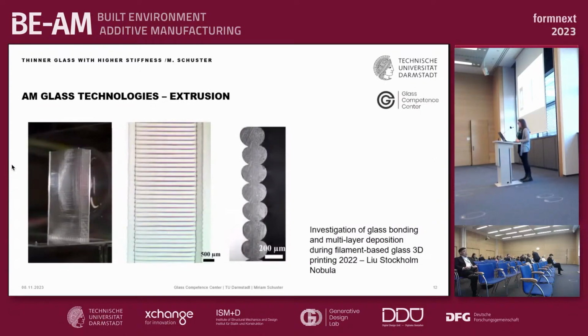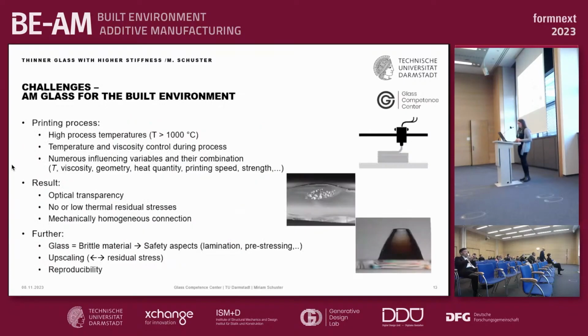This is by Nobula. And with this picture, I want to show that for all the extrusion-based technologies, we have in common that we are printing layer by layer. And when we are doing this, then, of course, we have the interface between the layers, and there are some notches, and those notches can be a weak point, especially for brittle materials such as glass. So what are the challenges? The challenges can be divided into different levels. The first level would be the printing process itself. Glass has a very high melting temperature of more than 1000 degrees Celsius.